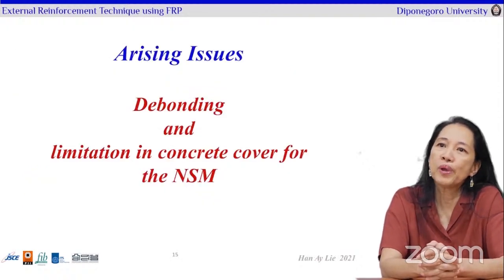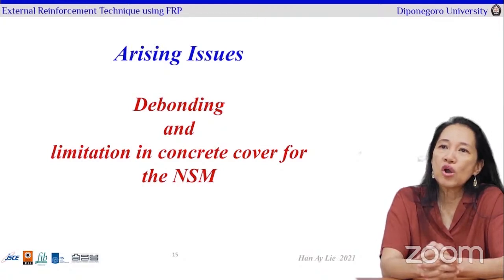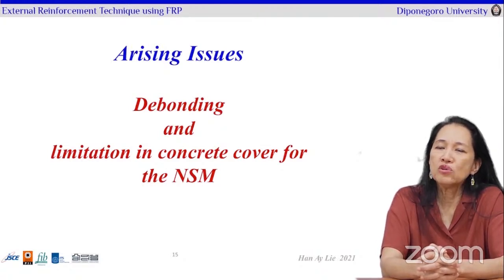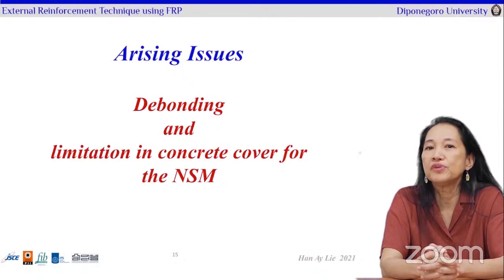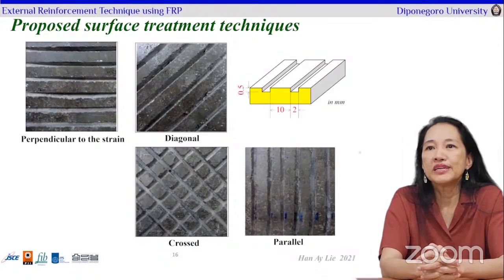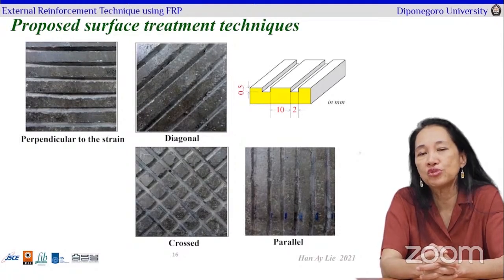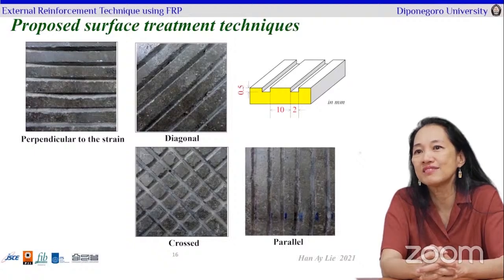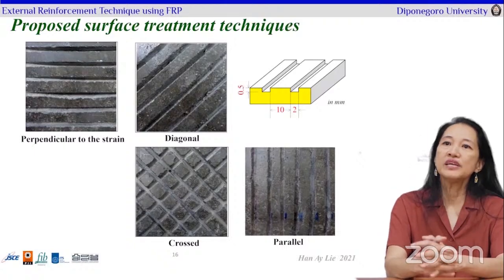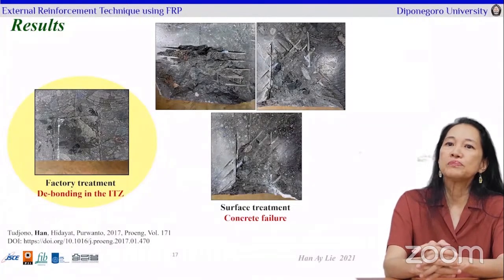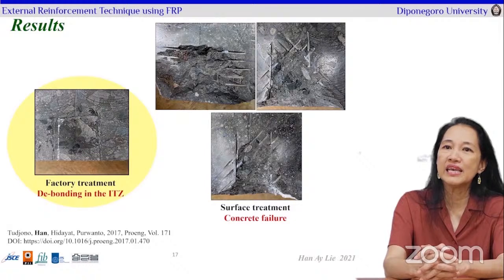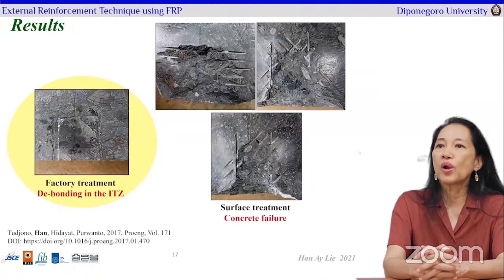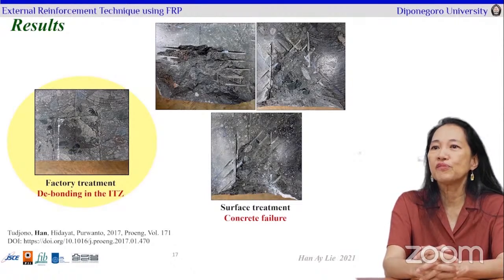So our issues, what do we have? During the test, we saw that debonding occurred. We also had the problem for the NSM that the concrete cover was not thick enough to fulfill the ACI codes. So what would we do about it? For the debonding, we proposed an additional surface treatment by putting grooves in the surface of the concrete, like you can see, we tested 4 types. And as a result of this, you can see that the factory treatment resulted in the debonding of the ITZ between the FRP and the concrete, but for all our treated surfaces, the concrete failed.